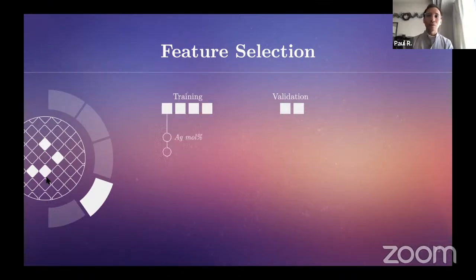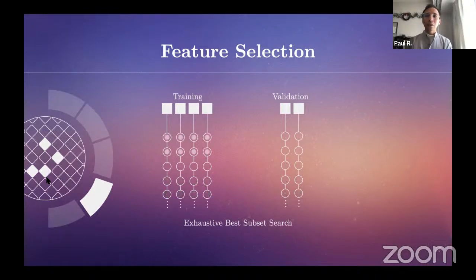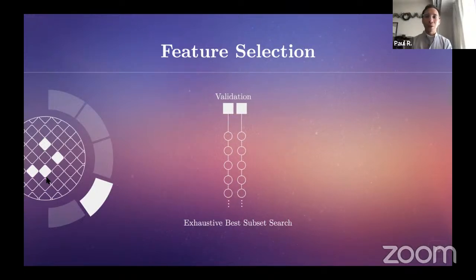For feature selection, we want to find the subset of features that produces the most accurate model. And since we only have a small dataset and a small number of features, we decided to perform an exhaustive search for the best feature subset. It took a total of 3,472 combinations of 5 out of 14 features, which ran on our computer for around 26 hours. Our program then scores each possible combination of features, and the combination or subset that scores the best is selected.